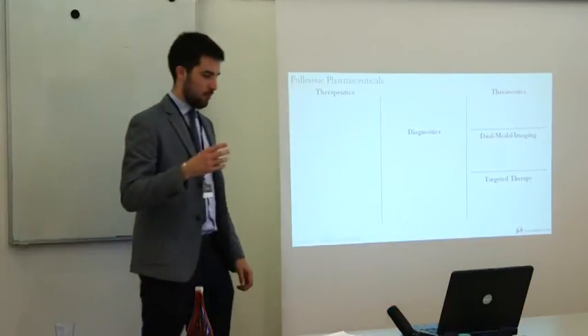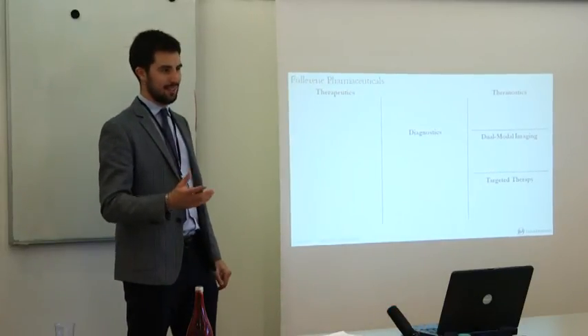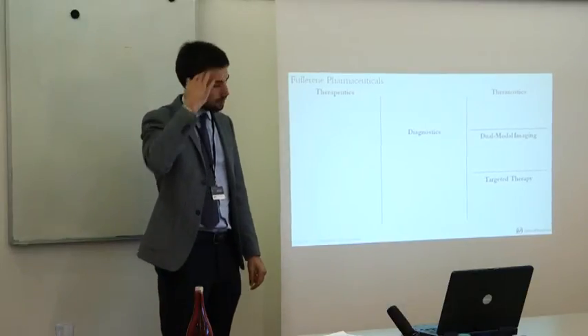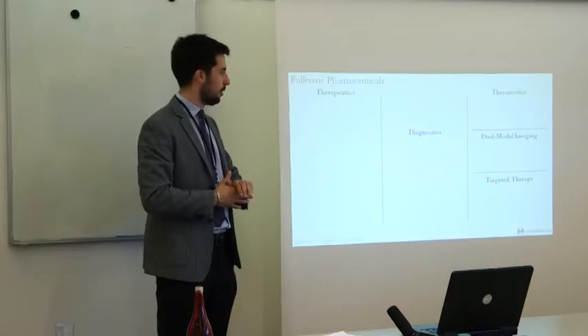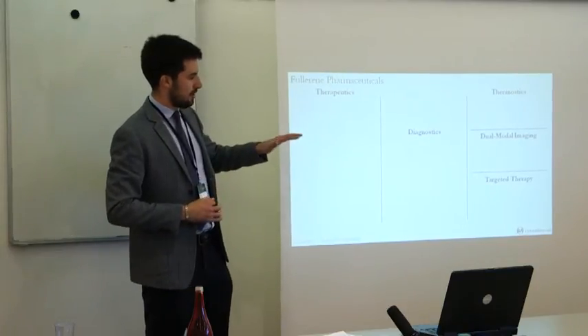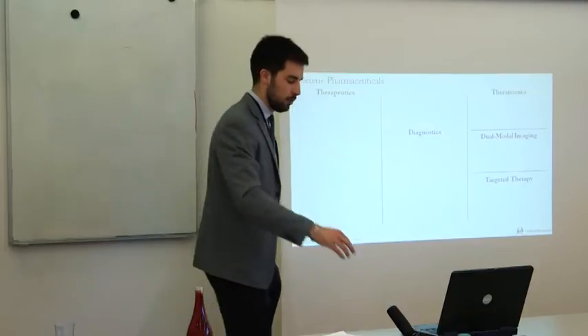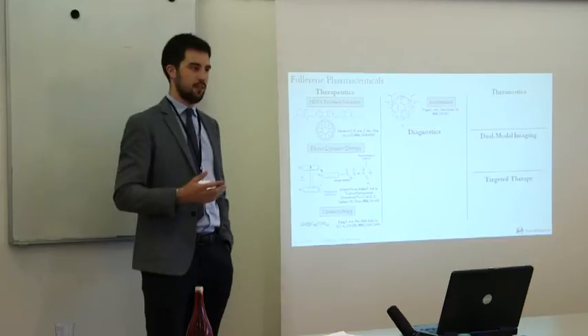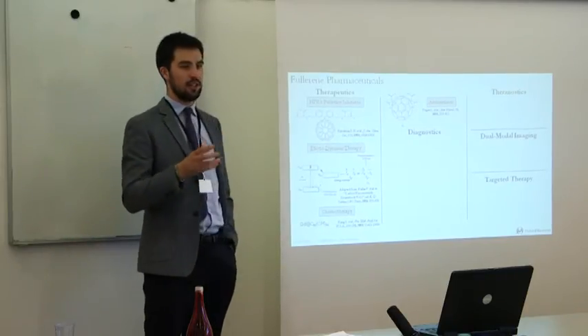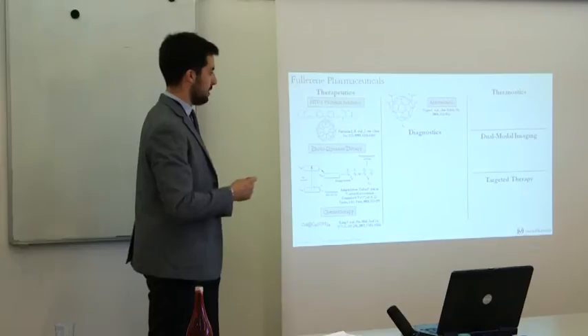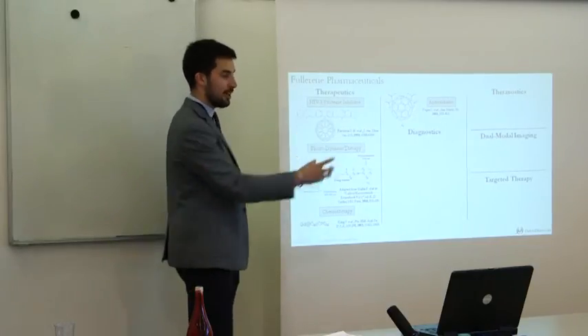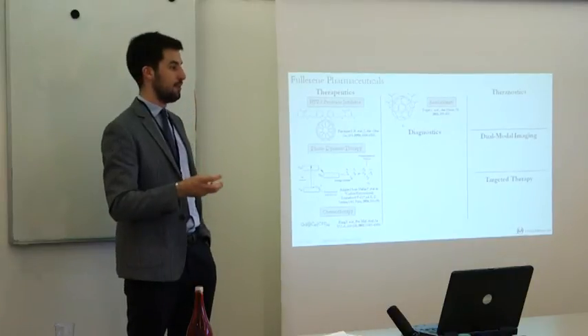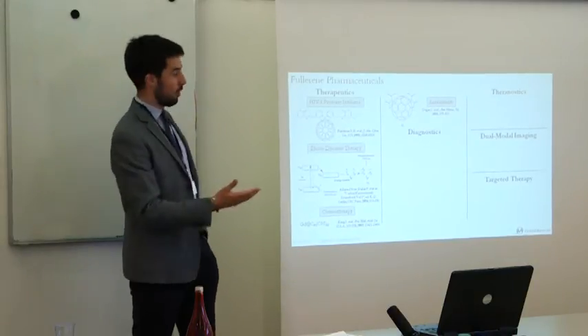Just to take three structures out of my lit review, common methods of water-solubilizing fullerenes. A really common one is polyhydroxylated, just attaching these hydroxyl groups and adding as many as you can onto the cage. Great, but you get a distribution of the number of additions to the cage, which isn't well-defined. It takes lengthy processing to isolate one structure. This one is C3 because of its symmetry. This one has been favored in empty cage fullerene studies for biomedical applications. This is just three malonic acid groups attached to the cage, and that's nicely water-soluble. Another one is this dendrofullerene. You actually don't try and maximize your water-soluble additions to the cage, but you make one addition and then water-solubilize that.